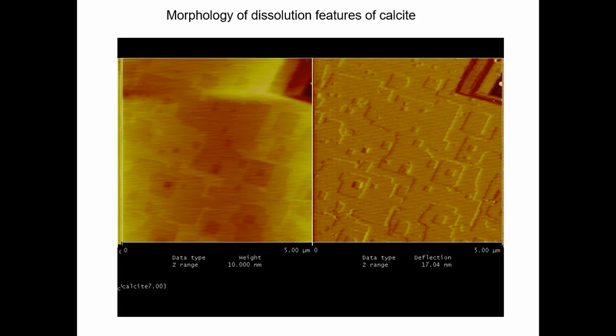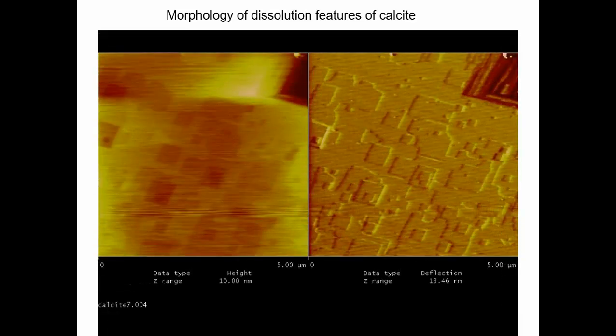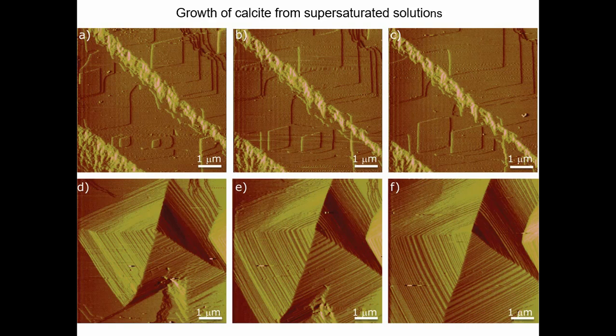Dissolution is very different all over the surface. So we're getting dissolution, the release of, in this case, calcium and carbonate over the surface. It's going to be different all over the surface. So the mineral fluid boundary layer is going to have a different composition across the surface of that calcite. Now, what about growth?